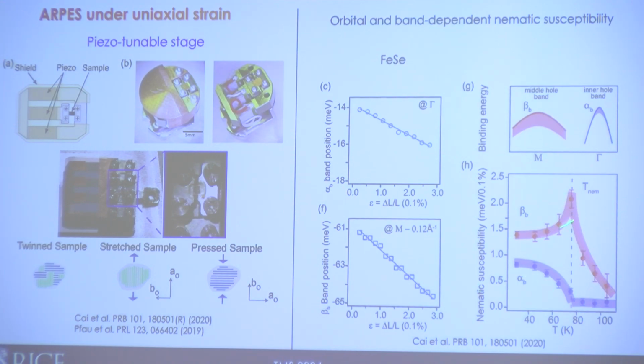And so nicely, you can see that you can do this kind of nematic susceptibility measurement in a momentum-resolved or orbital-resolved way. And very curiously for this material, what they see, to make a long story short, is that the response is highly momentum dependent. You can see the divergent behavior for the corner of the Brillouin zone, but for the gamma point, the center of the zone, it doesn't show this kind of divergent behavior.